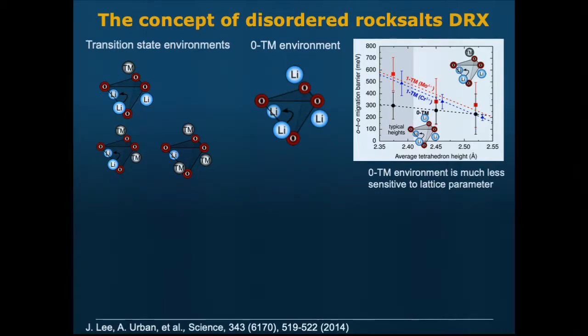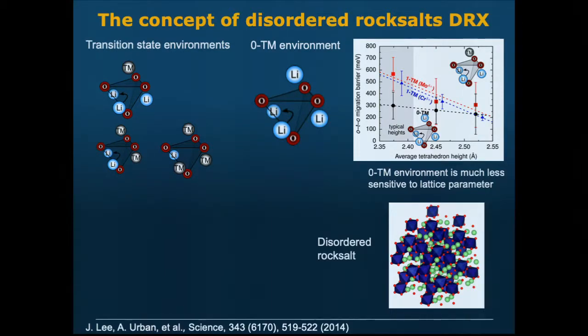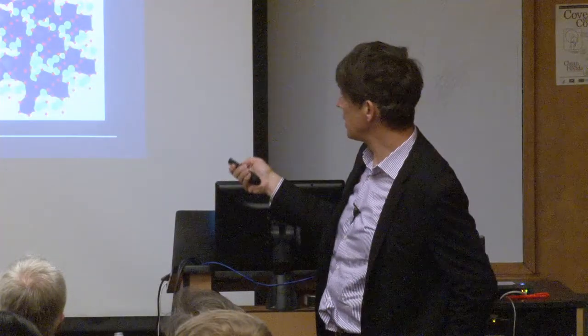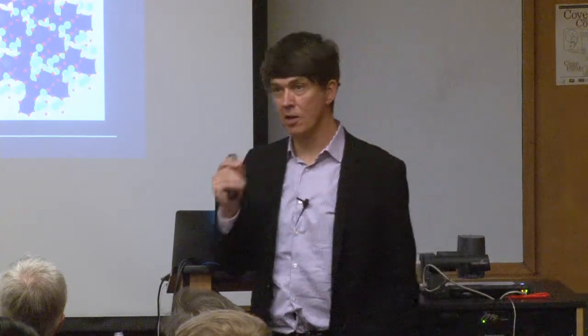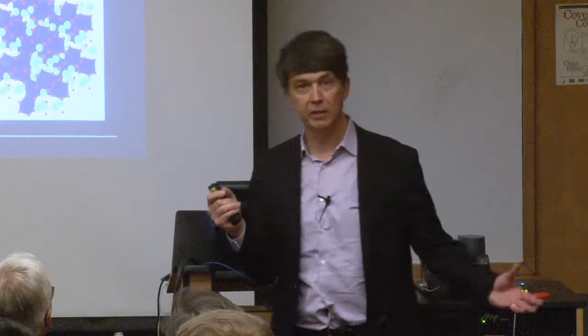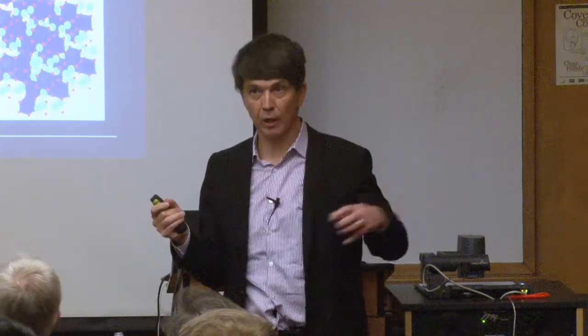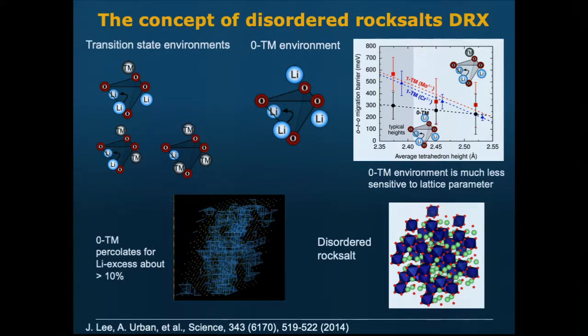Well, if you have ordered structures, in these layered structures, there are only 2 environments, this one and this one. And this one is the one you use. But if you were to disorder the material, if you were to start randomizing the cations, then you would statistically create all kinds of environments, right? And if you can make enough of these, you can actually get diffusion. So what we thought of is, can you make disordered rocksalts? So they're still crystalline materials, but the cations are now disordered, so that statistically I get some of these, and then can I make enough of them that they percolate? Because I need diffusion throughout the whole crystal, so I need what's called percolation of these environments. And it turns out that you can percolate if you put about 10% lithium excess in.